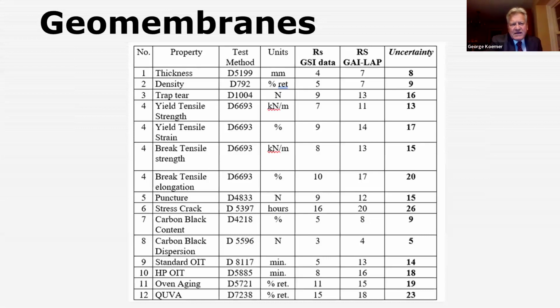The second group of data looks cleaner. This is for geomembranes, and it happens to be the membrane characteristics for GM13, which is our most reviewed and most referenced specification. We have thickness, density, tear, yield strength, tensile, puncture, stress crack, carbon black content, carbon black dispersion, OIT, both high pressure and standard, oven aging, and UV fluorescent. These numbers look tighter than the textiles, and it should be. The membranes are more repeatable and reproducible in their test methods, but it gives you a general flavor of this.